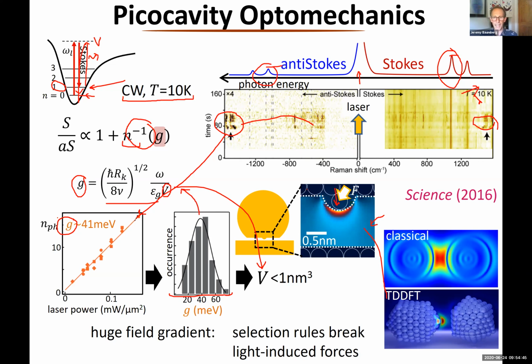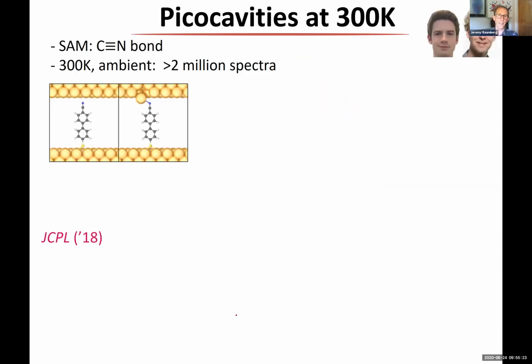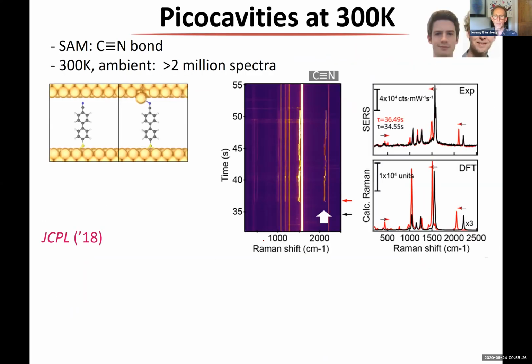And it's probably because the electrons in the gold here can go in and out very quickly. They're still free gold electrons. It would be different if we pulled the gold atom completely away from the facet. So a gold atom in the gap here would be completely different. But as long as it's attached to the facet, essentially it gives this a very strong optical field. The other thing that you can see is that the field gradient here is extremely high. So what it means is now that the optical field is varying along the length of a single bond. So what that does is it breaks all of the selection rules in the system. And indeed, we think they're like forces which are actually pulling out this gold atom here. So the net result is that we actually see single gold atoms being pulled out.